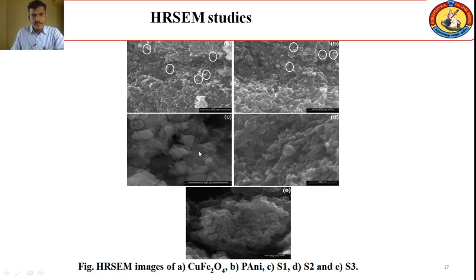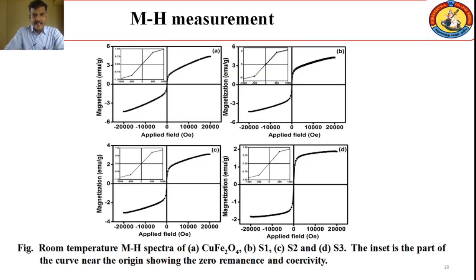In the case of S1, with higher copper ferrite concentration, all the particles get agglomerated. There are no spherical particles, because here copper ferrite is the dominating behavior, and the polyaniline is in very, very low concentration. Similarly, when you increase the polyaniline concentration, the particle size increases, which is around 88 nanometer, and when you increase the polyaniline concentration more, the spherical nature increases, and the average particle size is 98 nanometer.